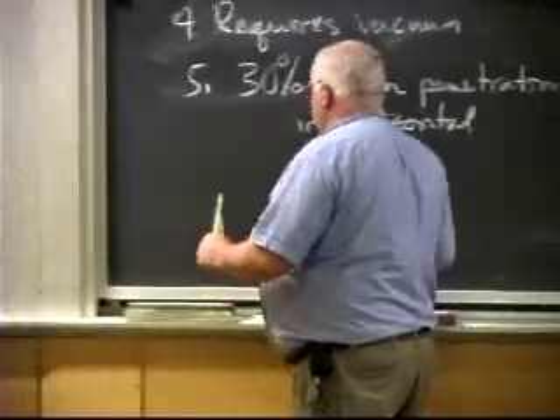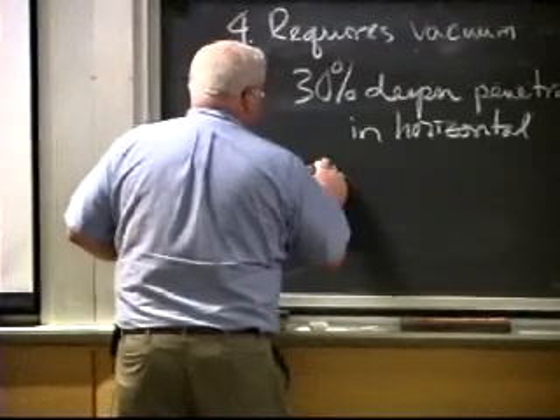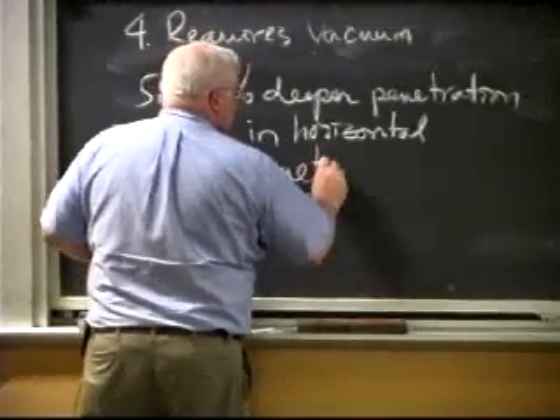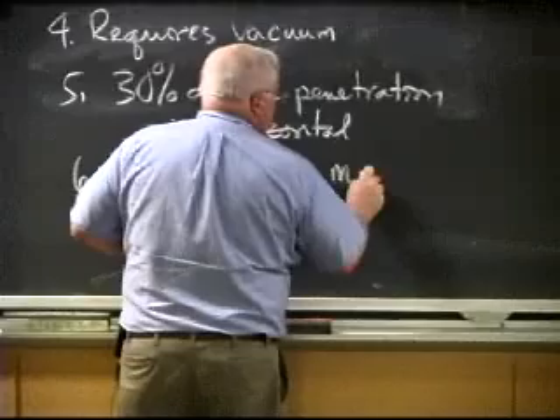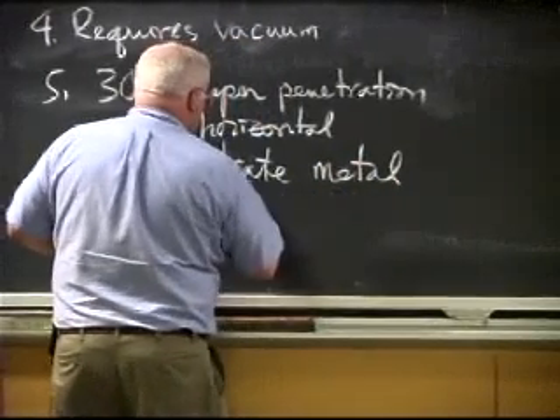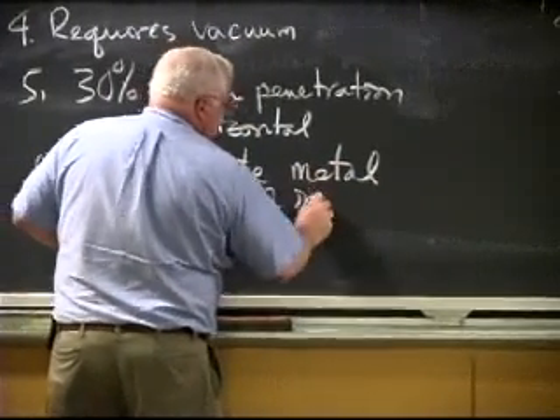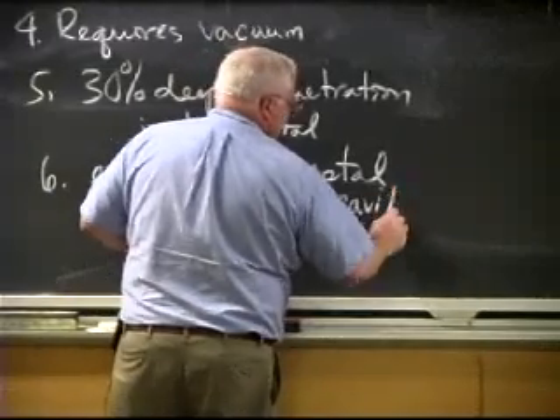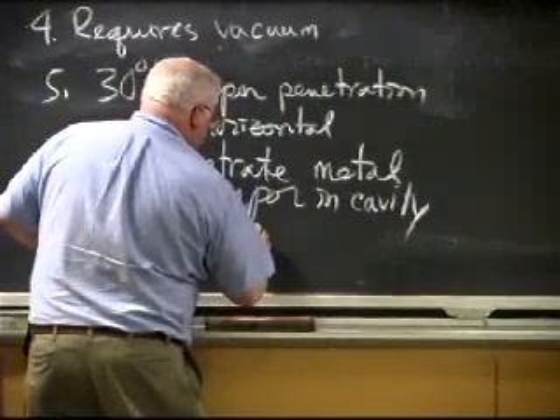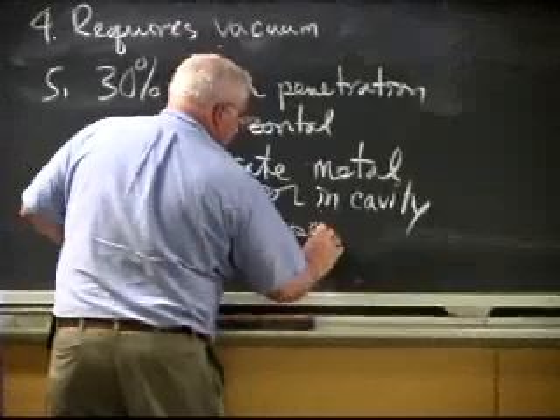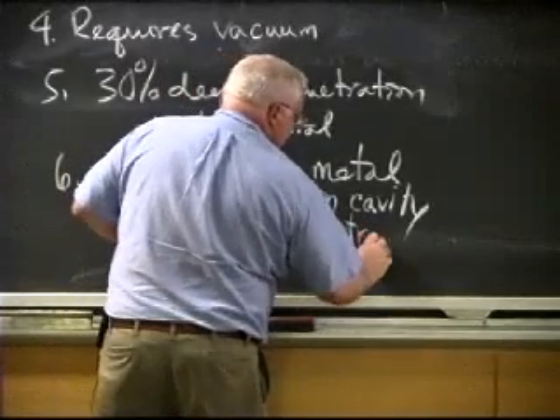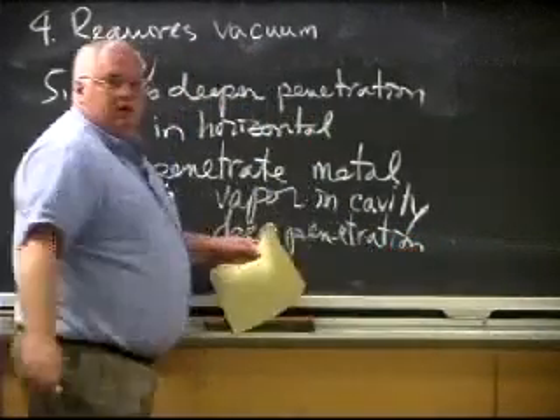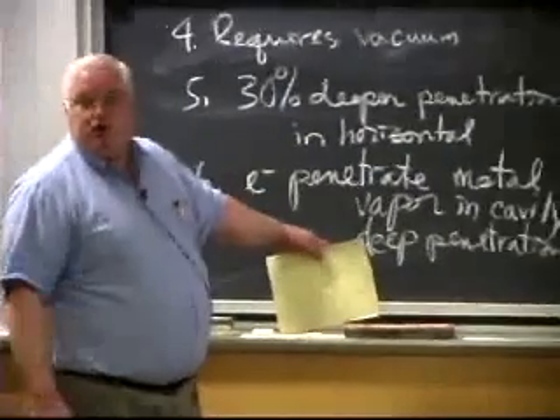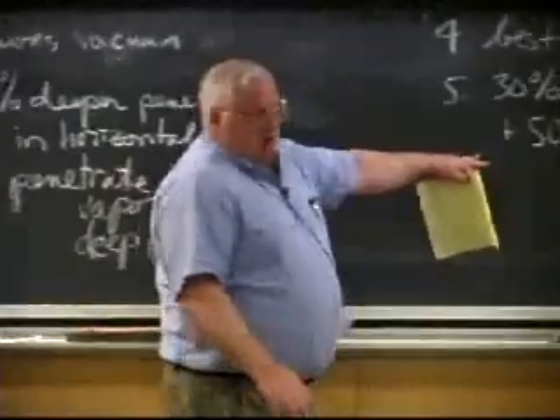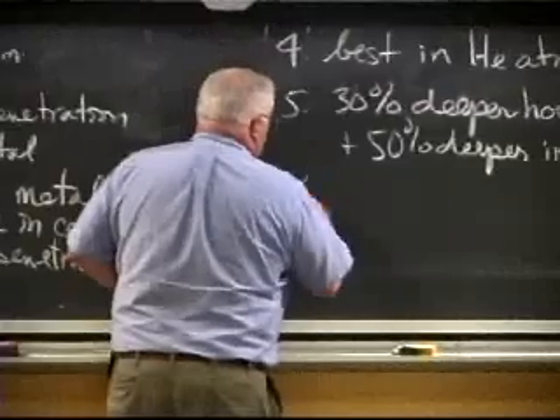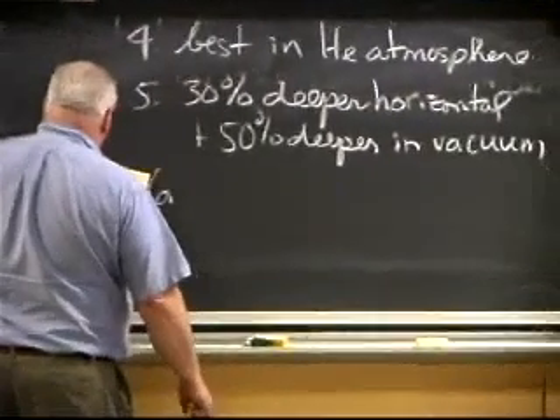So that's actually the next thing. Electrons penetrate the metal vapor, both on top of the cavity and inside the cavity. So you get deep penetration. With a 15 kilowatt electron beam, I can probably penetrate 2 inches of metal. With a 15 kilowatt laser, I may only be able to do a quarter as much, a half an inch or 3/4 of an inch or something like that.